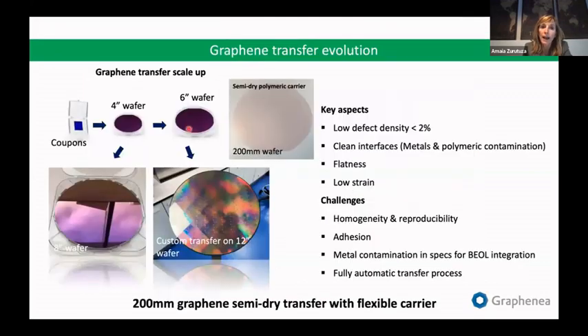Okay, and for the transfer, in a similar manner, we have experienced an evolution there. So from coupon level, like really small samples, to 4-inch wafers, 6. Here you can only see the wafer, basically, because I mentioned graphene is transparent. But this is an 8-inch silicon wafer fully covered with graphene. In this case, here we have a 12-inch or 300 millimeter wafer where we transferred a 200 millimeter graphene on it. You can maybe see it here at the edge of the graphene film. So it's a 200 millimeter. Hopefully in the future, when we move to 300 millimeters, we will be able to cover all that.